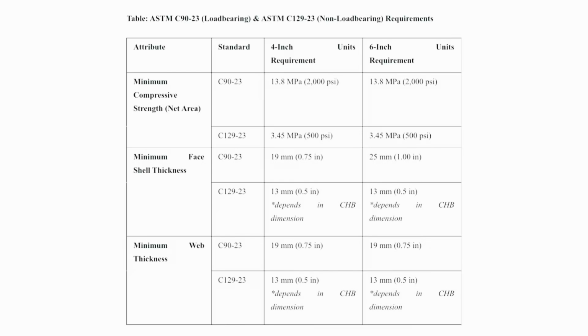Report. Laboratory tests were performed on the 4-inch and 6-inch concrete hollow blocks to determine their compressive strength and dimensional conformance to ASTM C90-23 and ASTM C129-23 standards. These tests were used to check the structural adequacy of the blocks to conform to standard specifications. The results showed that the web thickness of the 4-inch CHB conformed to the ASTM C90-23 requirement, but the shell thickness was inadequate. But the 4-inch CHB satisfied all the dimensional specifications by ASTM C129-23.